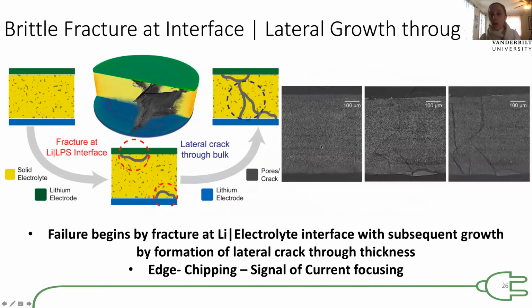But something we saw across all samples, and this was brought to light with the TEM, was that upon contact we see this edge chipping dynamic in all samples. This is located in the X-ray tomography data here. So we see this chipping effect that occurs at the lithium metal interface independent of the material we use, followed by this transverse crack that grows from one chipping site to another. This edge chipping is indicative of the current focusing that we saw with the garnet oxides, which suggests that independent of the material properties, the current focusing is a significant issue that may be overcome either through temperature or pressure control.